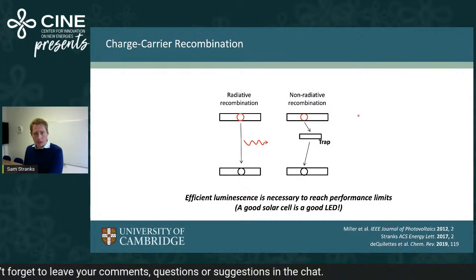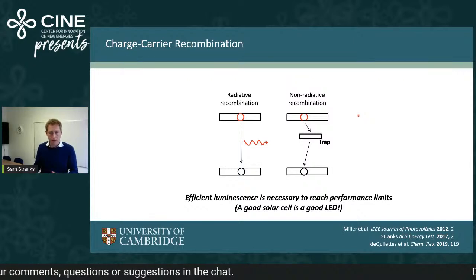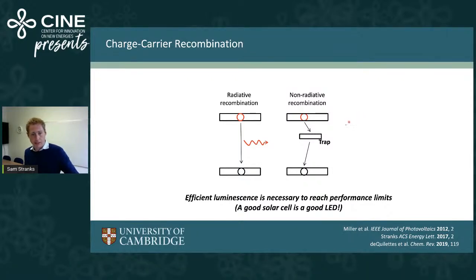So generally, we use light to understand these materials, and we use particularly the light coming out, and I just showed an example of that just then. And this is because when we energize electrons and holes, then eventually they'll recombine and emit a photon, so we can detect that light coming out. But we may have instances where we energize these electrons, but they hit traps, or they hit defects, and these are sites that can trap these electrons, and then they lose their energy to heat, so we can't use them for useful work. We can't collect that energy and use it for useful power.